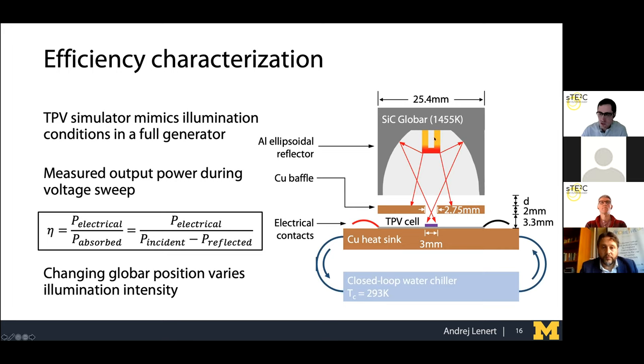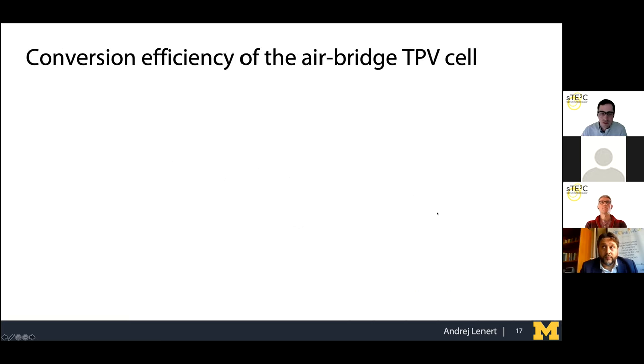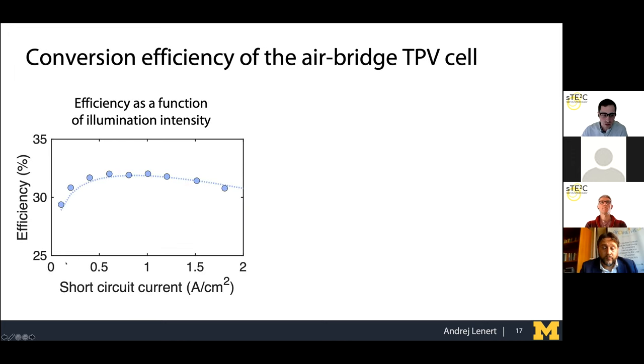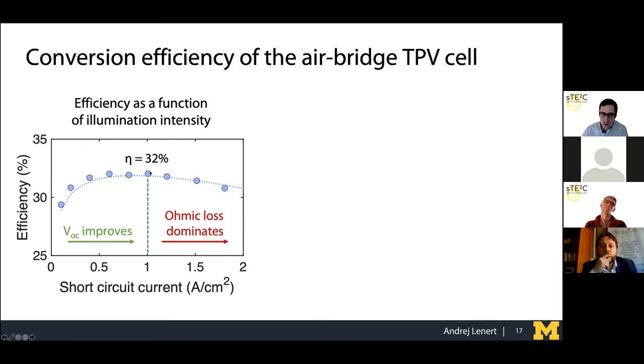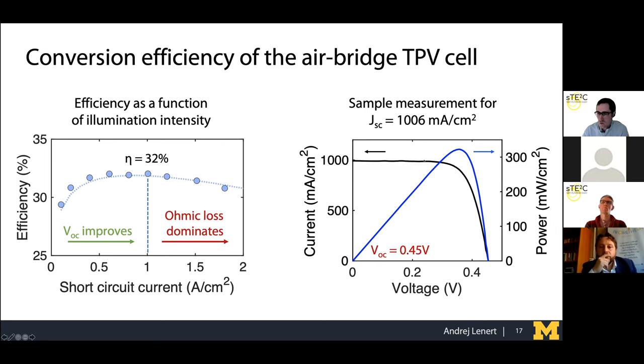And if we change the position of the thermal source, we can vary the illumination current. So what we show is that as a function of illumination current, we have efficiencies that approach 32%. As we go to higher illumination, closer to 1 amp per centimeter squared, the voltage improves. However, when we go to higher currents still, we're dominated by ohmic losses. And so this produces a maximum efficiency of about 32% near 1 amp per centimeter squared. And here is the current-voltage characteristic at 1 amp per centimeter squared.